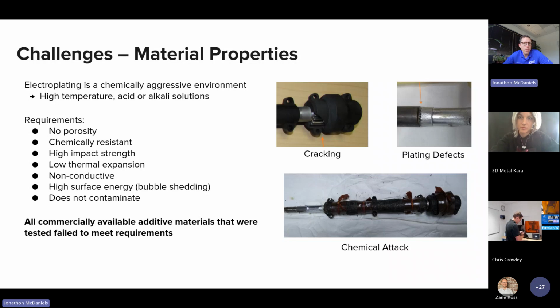It needs to have high surface energy, so it's got to be able to bubble shed. These plating baths tend to, when you apply current, generate hydrogen gas at the surface. So that needs to be able to shed away. If it doesn't, you can see some of this in that upper right picture, those bubbles are going to collect, and then that's going to mess up the plating.